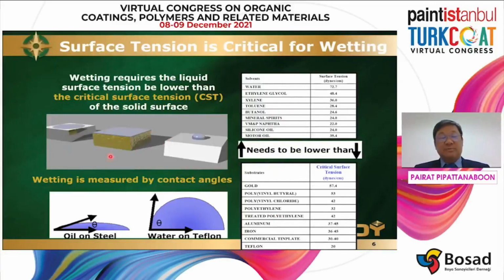Is that what you see from the cartoon here? Because water itself has a contact angle bigger than the silicone oil on the aluminum surface. So the contact angle that measures the wetting ability is a key parameter that we can perceive, showing how the solvent can help the coating on such a contaminated surface or low energy surface.